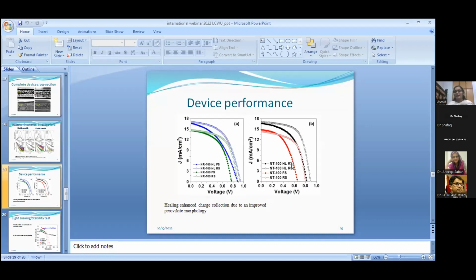One thing is more interesting, which is evidence from our previous slides, that the VOC is maximum. We got the maximum VOC in the healed nanorods, which says that the crystallinity of the nanorods is good and we have less interfacial charge recombination. So healing enhanced the charge collection due to an improved perovskite morphology.